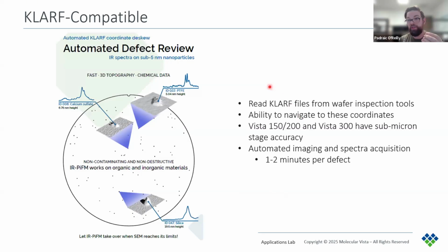A wafer inspection tool such as SurfScan from KLA uses lasers to quickly scan a wafer and create a file with the coordinates of the defects that it detects. So we can take these files and load them into our software and navigate to these coordinates with sub-micron stage accuracy. We've also developed an automated mode that will navigate to user-selected defects for you.